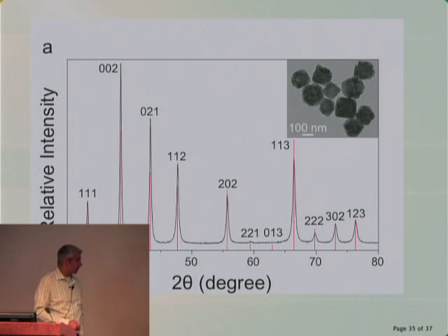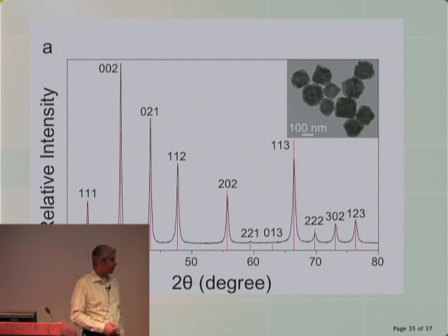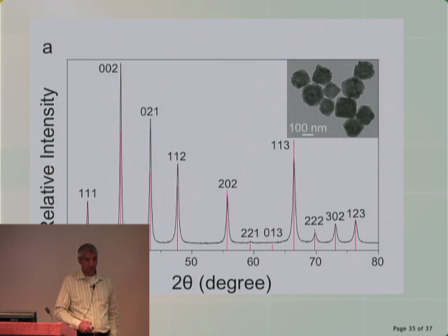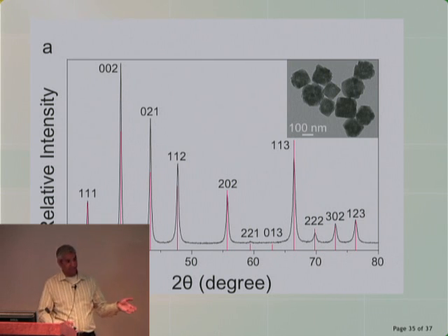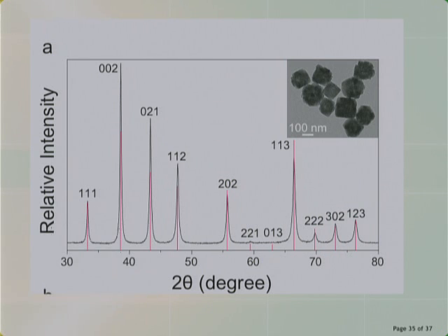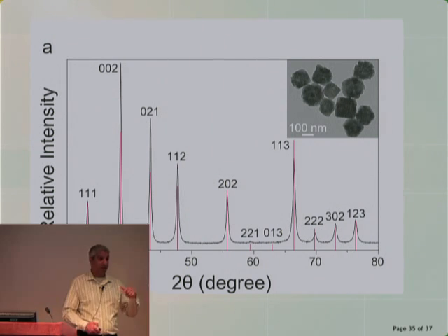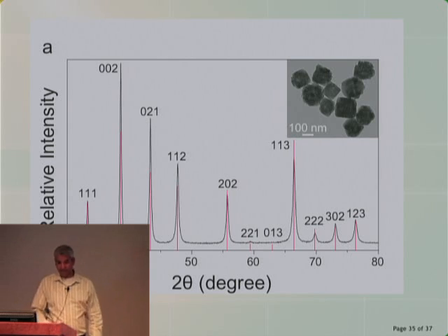Well, to bring you back to an X-ray diffraction pattern, which we talked about earlier as a way of knowing the crystal structure, this basically represents, again, the red lines are where the peak should be for a pure pyrite sample, and this is our sample. So we believe we have one of the first very pure synthetic pathways for producing phase pure pyrite. And that's an exciting development because that's, in some ways, a harder problem for us to get the phase exactly where we want it. Now we're working on figuring out ways to either grow those smaller or to actually deposit them in a film and test the electrical properties. That's sort of next on the list.